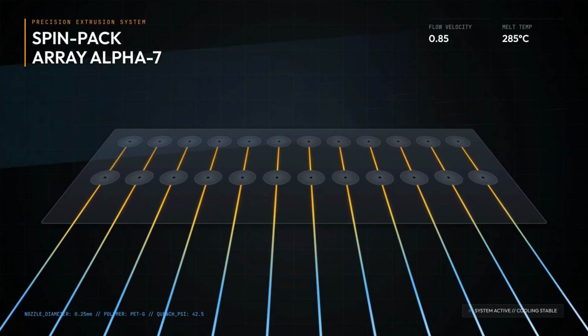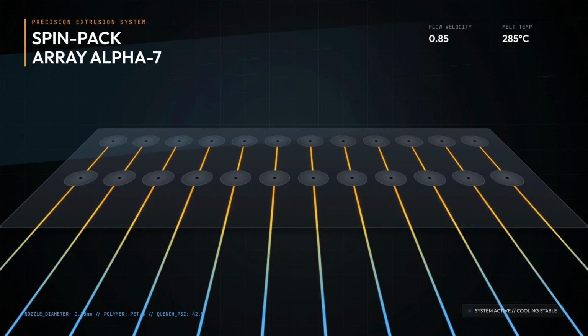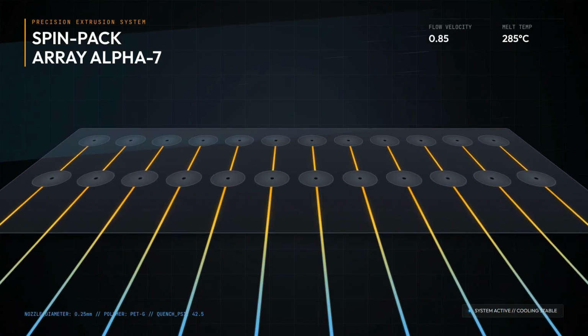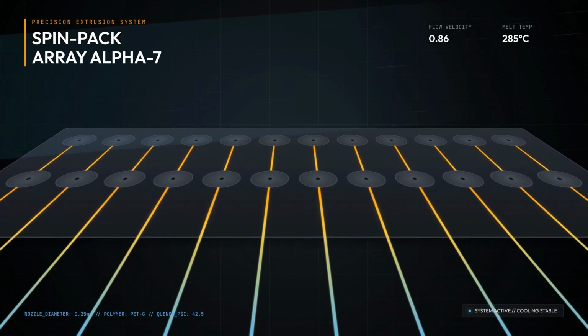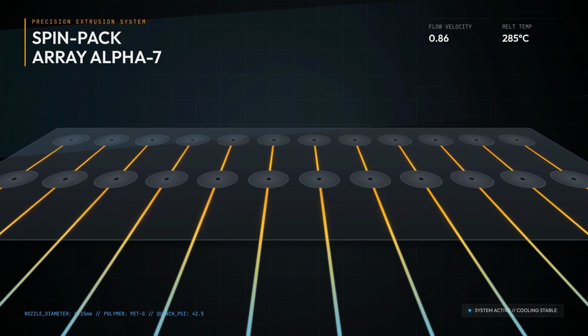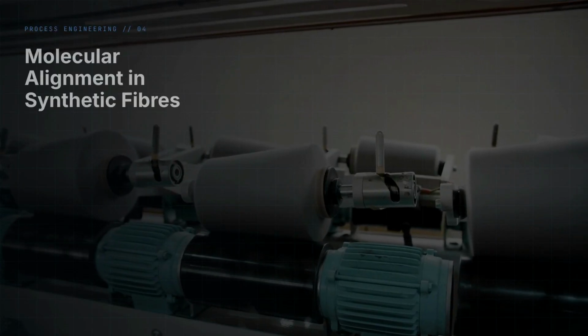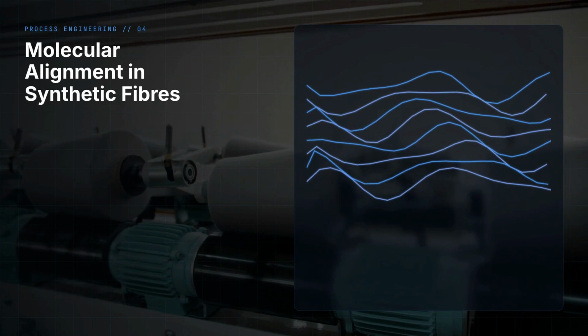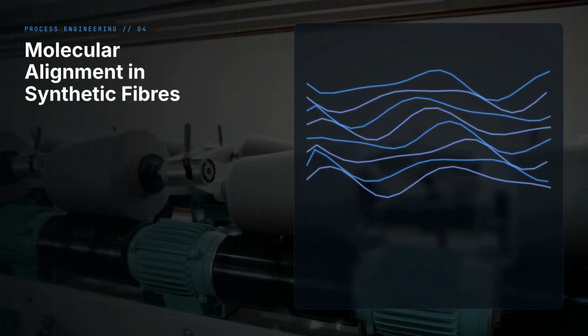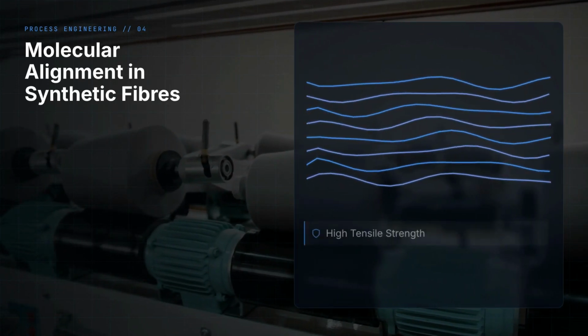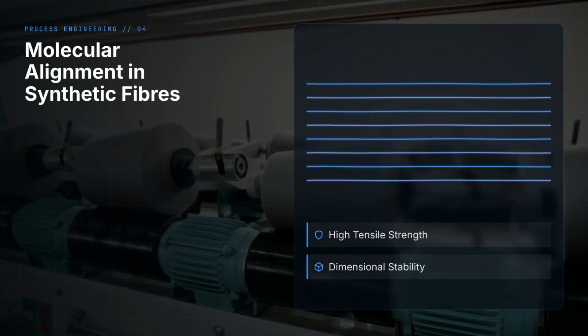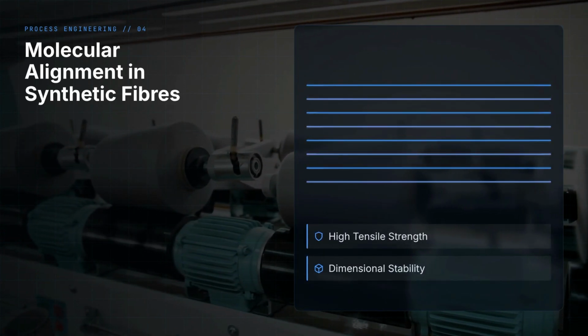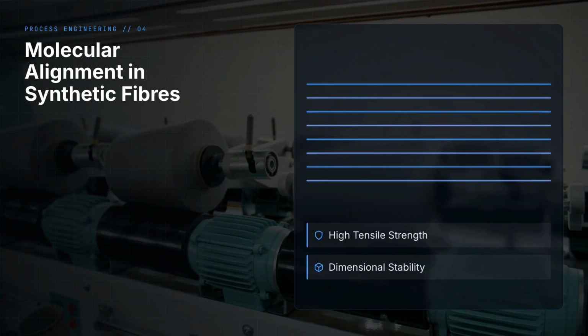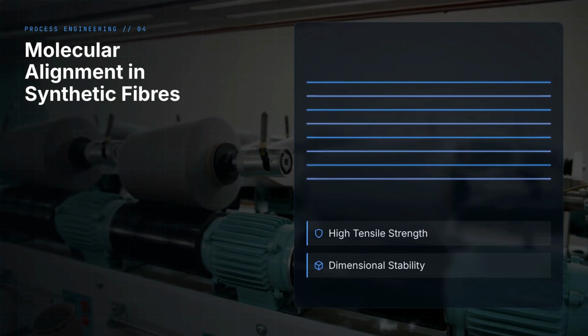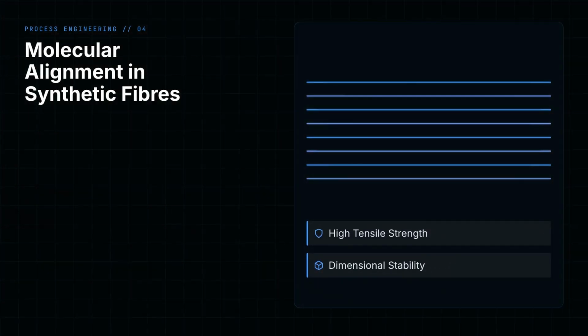Each microscopic spinneret hole forms one continuous molten filament. As the filaments leave, carefully conditioned quench-air rapidly and uniformly solidifies the polymer. Next comes drawing. The yarn passes over Godet rollers operating at different speeds. Stretching the yarn aligns the tangled PET molecules, dramatically improving strength, stiffness, and dimensional stability. This process determines if the yarn is POY, FDY, staple fiber, or higher tenacity industrial yarn.